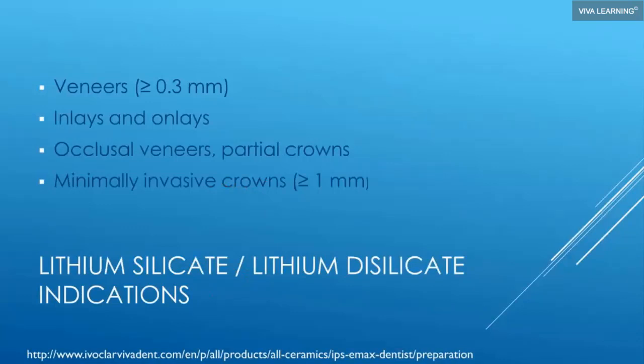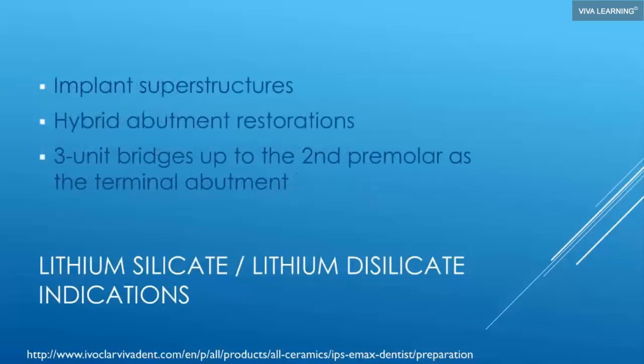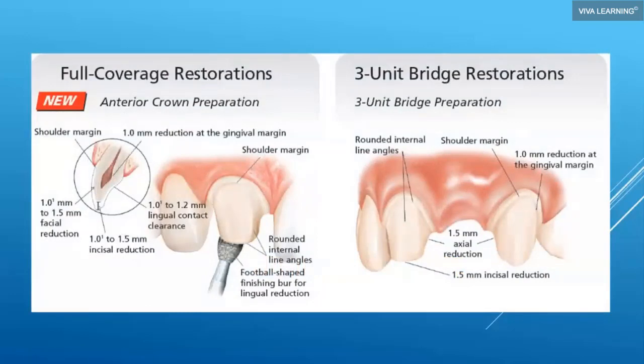When would I use lithium disilicate? Inlays and onlays, veneers, minimally invasive crowns, all work well for lithium disilicate. Can you use it in the posterior? Absolutely you can. You can use it for implant superstructures, 3-unit bridges. There's really a lot of options where you can use your lithium disilicate. Again, one huge advantage of lithium disilicate is you can truly bond it into place. You can cement or pseudo bond into place zirconia, but if you have a short preparation, you may want to consider a lithium disilicate crown that you can actually bond into place.